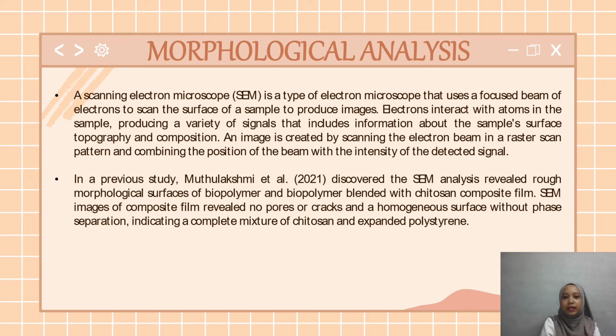In the previous study, Muthu Lakshmi et al. 2021 discovered the SEM analysis revealed a rough morphological surface of biopolymer and biopolymer blended with chitosan composite film. SEM image of composite film revealed no pores or cracks and a homogeneous surface without phase separation, indicating a complete mixture of chitosan and expanded polystyrene.